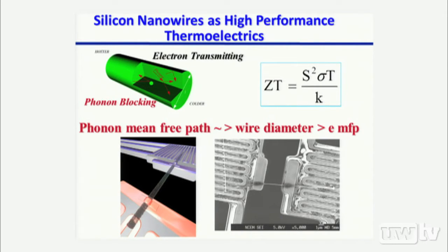When we talk about thermoelectrics, one of the very important physical parameters is called ZT, the figure of merit. Within this parameter, we have three fairly important physical properties. One is the S value and the sigma, which are the thermopower and the electrical conductivity of the semiconductor. They are related to the electron transport within a semiconductor. Then the K is the thermal conductivity of the semiconductor. So in principle, for high efficiency thermoelectrics, ZT has to be as high as possible. High ZT leads to high energy conversion efficiency.